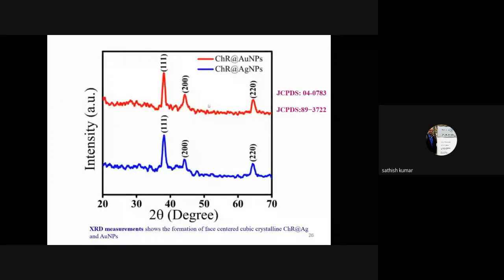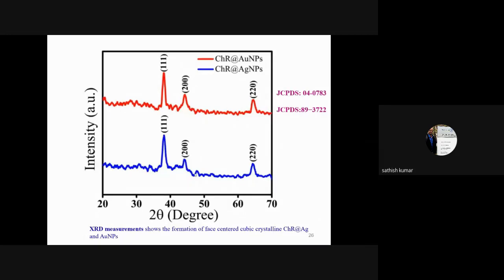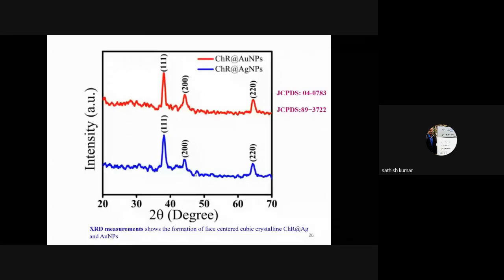Coming to XRD, XRD is used for the analysis of crystalline nature of the nanoparticle. So this study will give information about the crystallinity and the crystalline phase of the nanoparticle. The X-ray diffraction planes will be interpreted with the JCPDS standard value. So here we found that the diffraction value corresponds to the face-centered cubic silver as well as the face-centered cubic gold nanoparticle. So this is also another important thing, that we have without any mixed phase of hexagonal or other mixed phase. We have identified a single phase nanoparticle. This is because of using the polyphenols, the single biocompound, as a reducing agent.